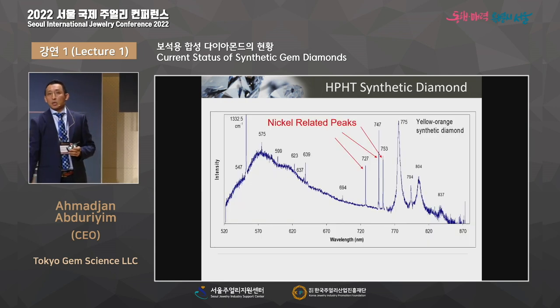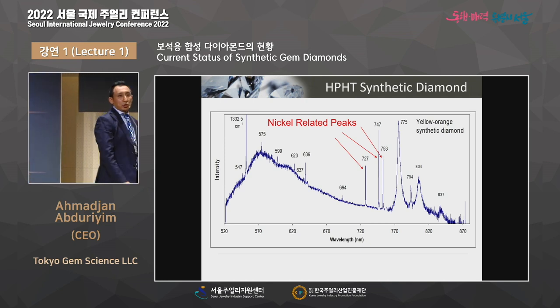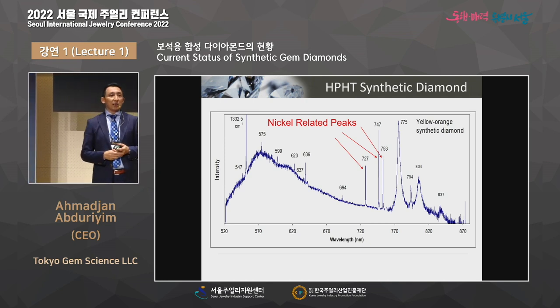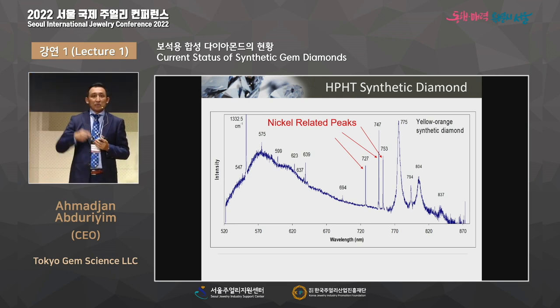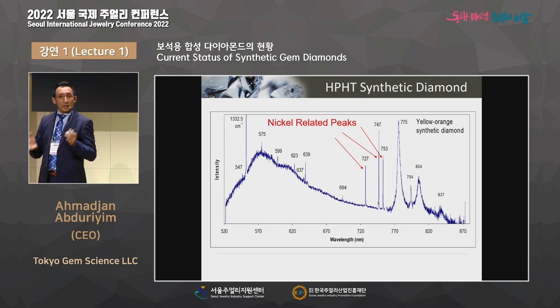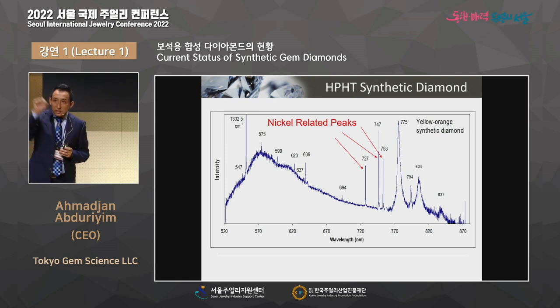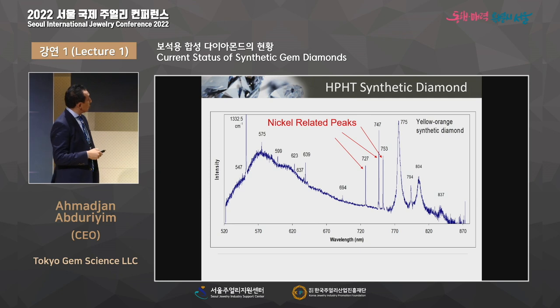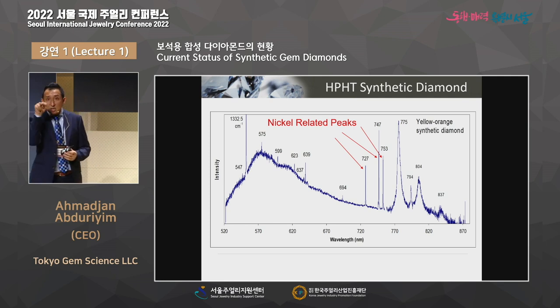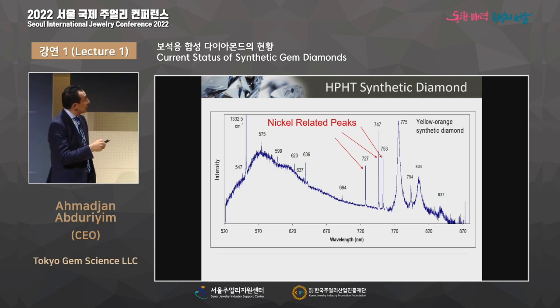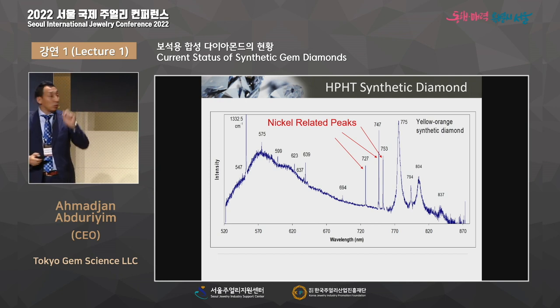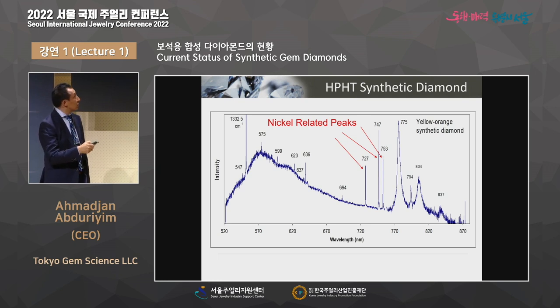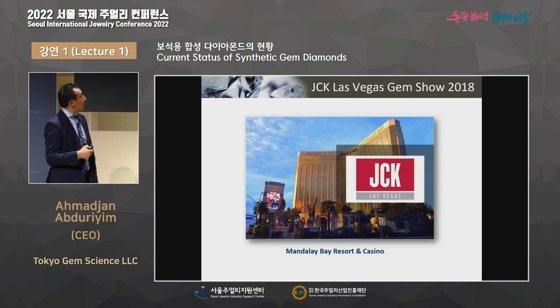And the more technical instrument is Raman spectroscopy. That is a very advanced instrument that uses a laser, green laser or blue laser, to check the defects in the diamond. With photoluminescence, we take the photoluminescence spectra, and we can detect nickel. This nickel you can never see by your naked eye. However, this instrument can pick up this kind of spectra to tell you this is exactly from the metal solvent. You can 100% diagnose that this one is synthetic as well.